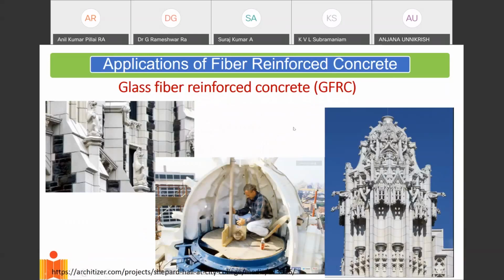Just an example of architectural restoration where these figures and figurines were essentially made in stone. They were replaced by glass fiber reinforced concrete cast elements, where the glass fiber basically holds the material together and doesn't allow it to crack.